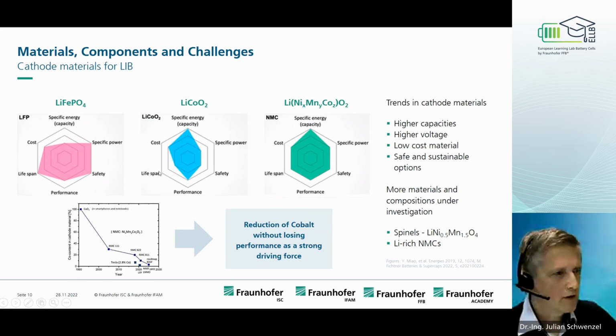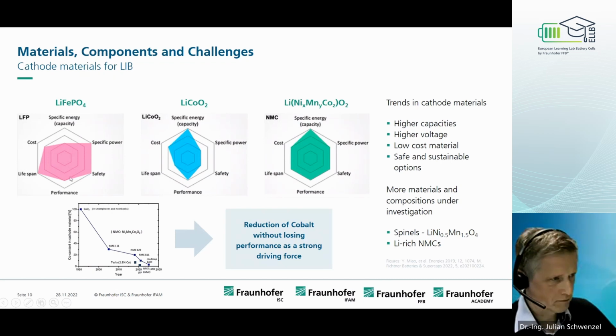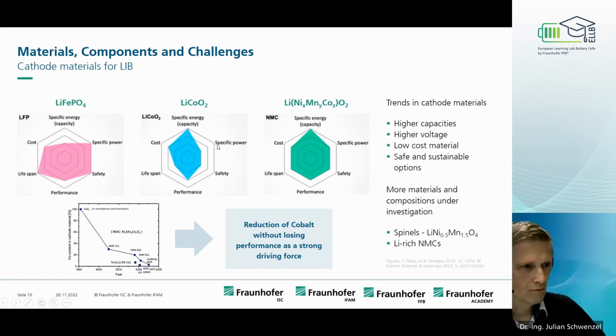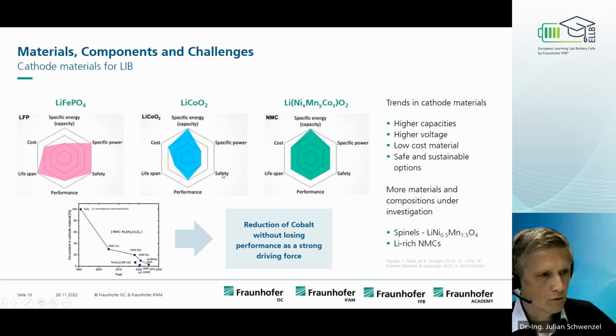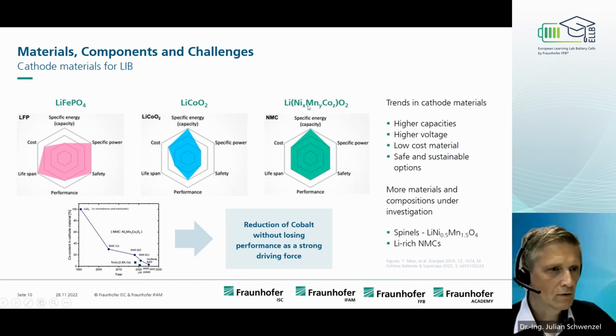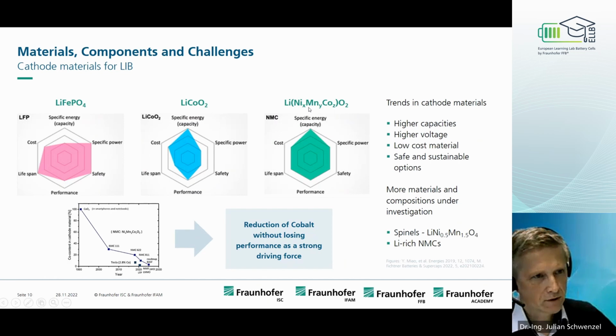But if you see the lifetime, it will not be so comparable with the iron phosphate system, or also with the power. And safety is also very critical because we have oxygen inside. If you discharge this material too much, you can release oxygen inside the system, and this will be a problem. Or we have another kind of layered structure material, well known, the lithium NMC, lithium nickel manganese cobalt oxide system, with different kinds of stoichiometries or a different kind of mixture.